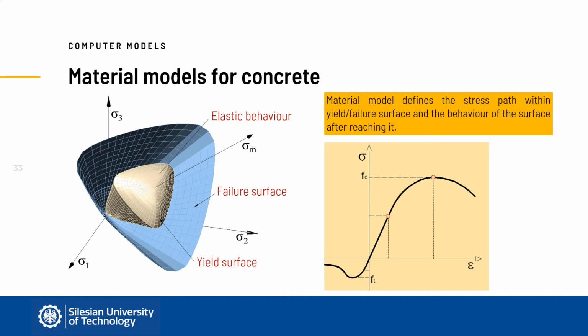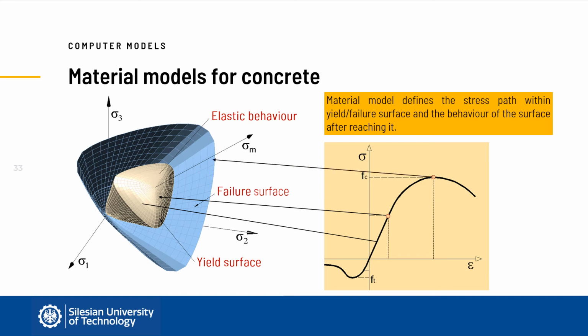As long as stress is below the elasticity limit of concrete, the material behaves in an elastic manner and the point representing the stress is inside the yield surface. When the elasticity limit is reached, it means that the point is on the yield surface. Now the applied flow rule defines the behavior of the material under increasing strains. In case of isotropic hardening, this is manifested with uniform growing of the yield surface until it reaches the failure surface and coincides with it. This means that the material has reached its compressive strength in this point.